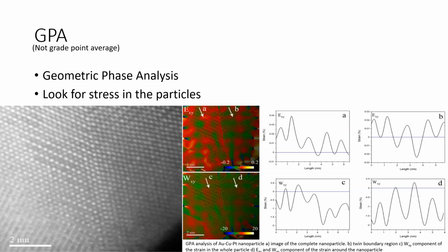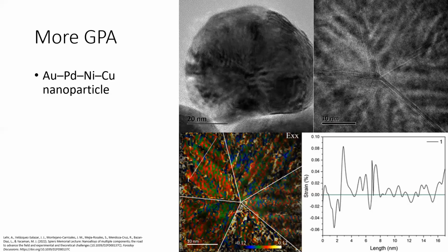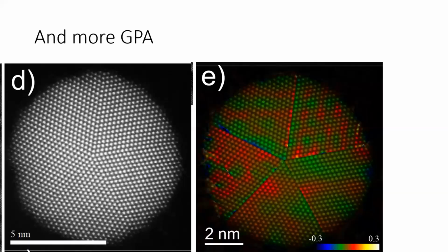It's really cool to see this periodic behavior, and it appears throughout tons of these nanoparticles in different areas. Here is a nanoparticle with four metals in it, doing this across the twin boundaries. Again, something almost periodic is going on with relieving that stress. And even with some of the small ones, between those boundaries, there's almost this periodic behavior going on within the particle. You can't really see it by eye, but there are tiny, minute changes in the distances.